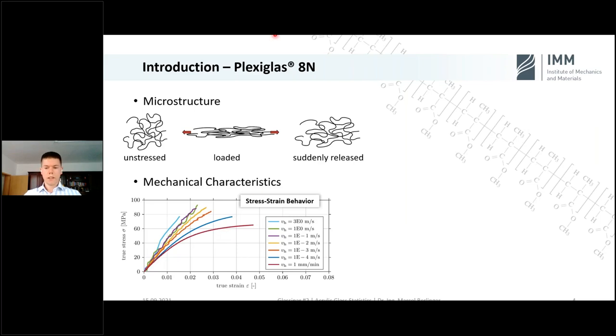Okay. Here we have our stress strain curves. You can nicely see that at lower velocities, that is this curve maybe of a single tensile test, we have a higher strain, but a lower limit of the stress. And with increasing strain rate, our curves do stiffen and the level of the strain is reduced.